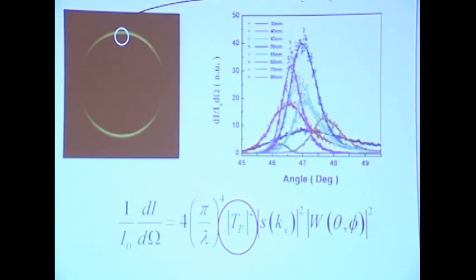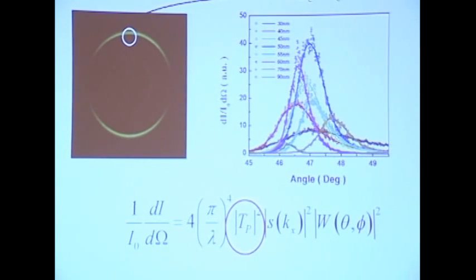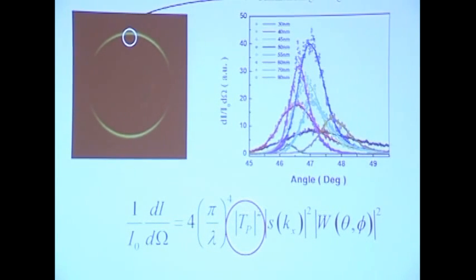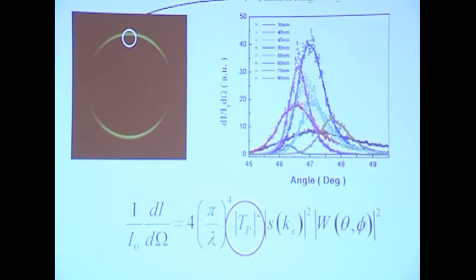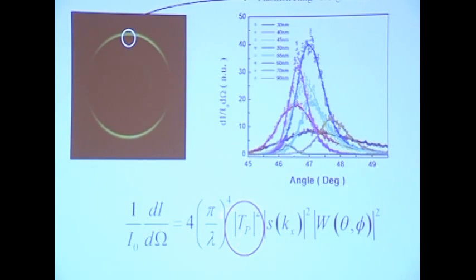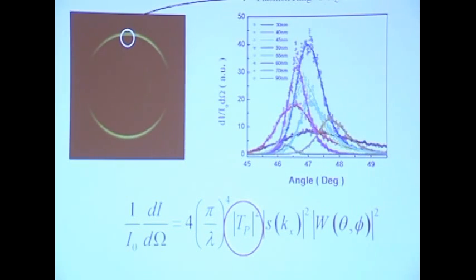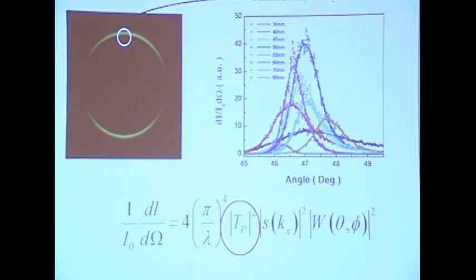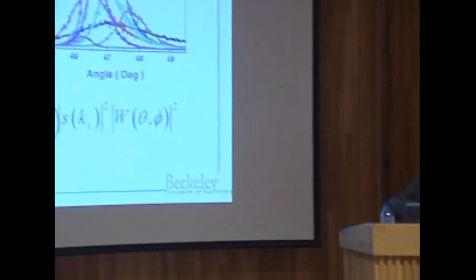Essentially, you can treat this as weak scattering because the surface roughness is only nanometer scale. So this is typical weak scattering optics, where the TP is what we want to determine, and this is what we measure here. And SK is the surface Fourier component of the randomness, which is a coupling strength. You can use AFM to map out the surface roughness and do a Fourier transform, and that's the Fourier component. Essentially, it's a coupling strength for this given K.